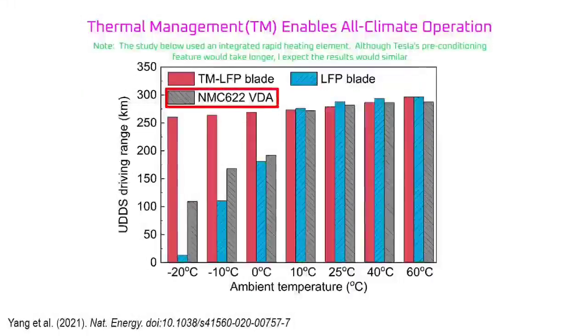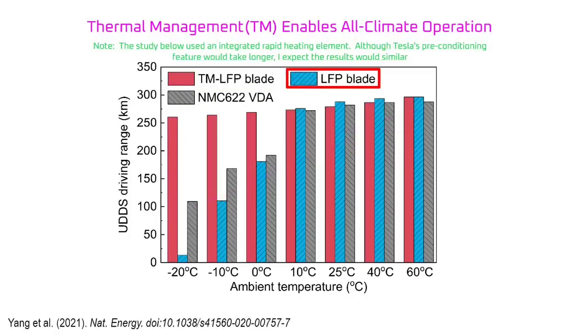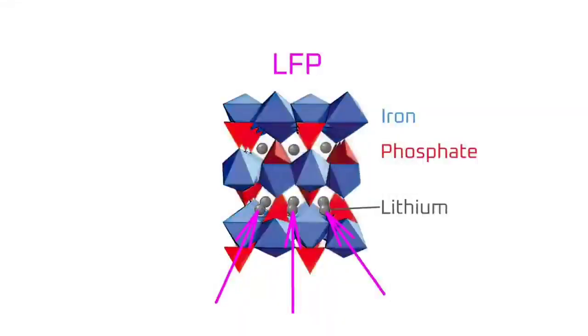The gray bars in this image show the performance of a high nickel chemistry similar to NCA from -20 Celsius to 60 Celsius. The blue bars show an LFP chemistry in a similar temperature range. As you can see, below 0 degrees, the nickel chemistry drastically outperforms LFP. The reason for this goes back to the 1D crystal structure of LFP we discussed earlier.